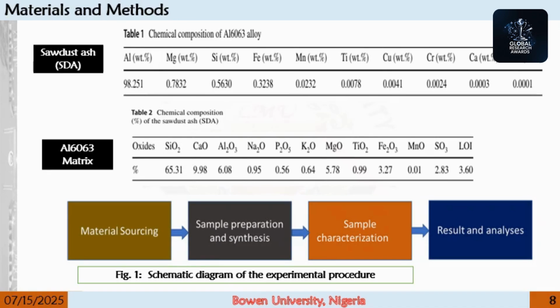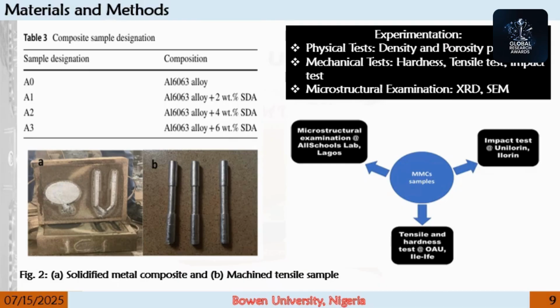So Figure 1 shows the method by which these materials are produced and the extent of carrying out the results: from material sourcing to sample preparation, sample characterization, and result analysis. Now, Table 3 displays how it was designed. A0 designation means that it's the control sample, the unreinforced alloy matrix, while the other ones are reinforced with 2%, 4%, and 6% of the sawdust ash. After production using the stir casting method, Figure 2 ensued, where we have the solid metal composite from the stir casting, and it was later machined to produce the tensile sample as shown in Figure 2b.